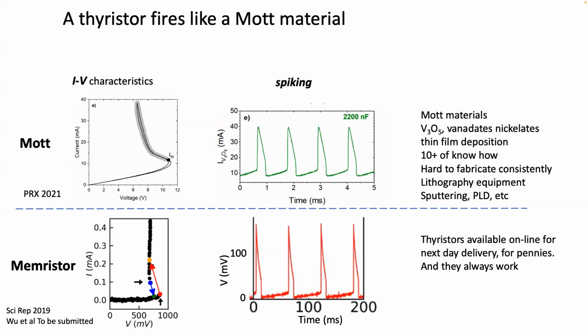To demonstrate this more evidently, this is a recent work with a group of Ivan, done with a Mott material. This is a V3O5, and it has an IV characteristic with a high resistance, low resistance, hysteresis, and when you apply voltage, you get spiking, and this is done with a memristor. This is work done with Jamin Wu, my student, with Olivier Schnegans and Kang Wang at the lab. And you see here the IV characteristic with the hysteresis and the spike generation that looks qualitatively like that.